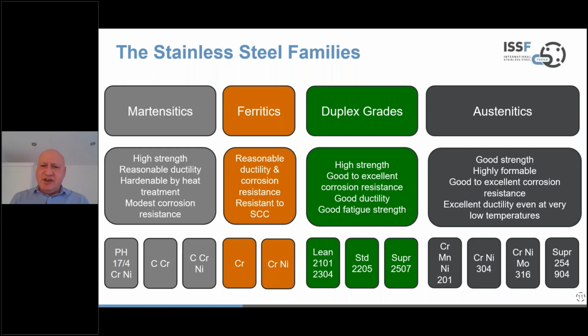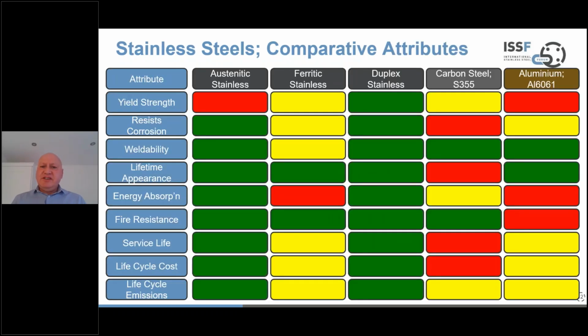So they're the families, but I would argue when we're thinking construction, we should be looking at the duplex grades and the austenitic grades first and foremost, depending on the application. Now, I think it's appropriate to compare attributes of stainless steels versus some other common materials that may be chosen. In this case, I've put the austenitic, ferritic, and duplex stainless steels alongside each other and then compared them with carbon steels and aluminium, a common aluminium alloy. And this is simply color-coded for ease of understanding. So red is bad, green is good, yellow is somewhere in the middle.